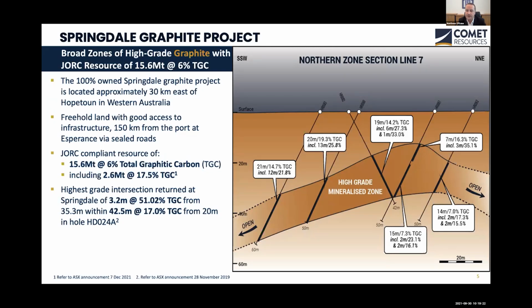We have some very high grade intersections there, and as I said, some very thick intersections too. So what you have now is a deposit that's very close to surface, with very thick zones of mineralisation, and so this should be quite easy to mine, a low cost open pit should it be developed. It's also on freehold land, very close to infrastructure and ports, sealed roads, so CapEx would also be quite low, we would expect, in developing this project. So very good from both an OPEX and a CapEx perspective from the information we have at hand at present.